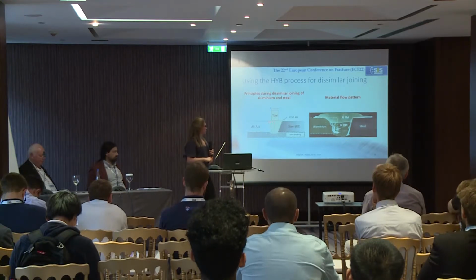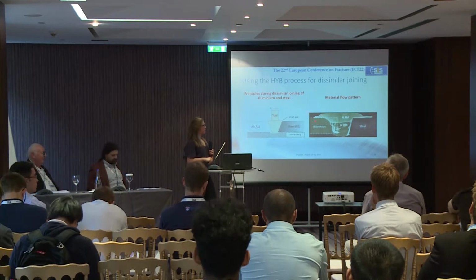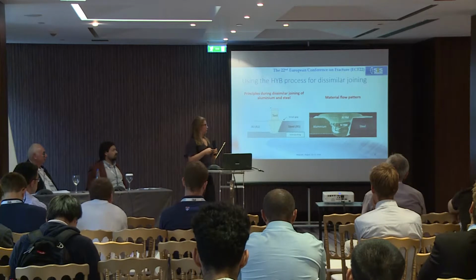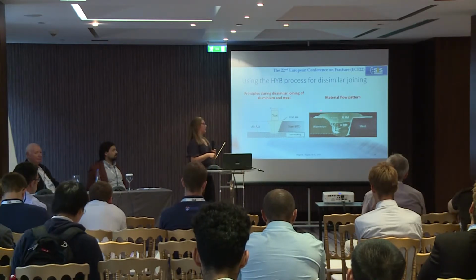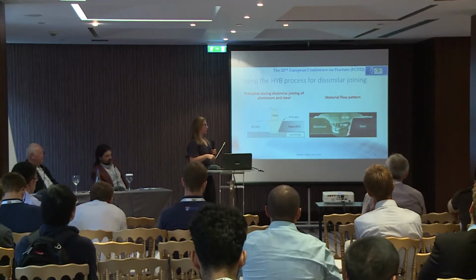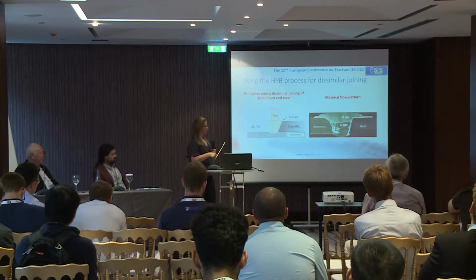So when the pin rotates, some of the aluminum base material will be dragged around with the motion and mixed with the filler material, which is extruded into the weld groove. So the filler material will flow from the upper region and down along the steel side, and some of the base material will be dragged from the aluminum side and mixed with each other.